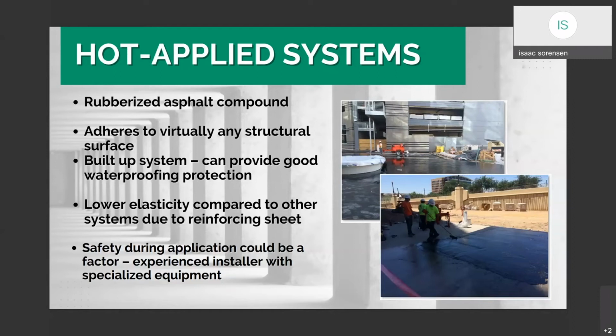where they put down like 180 mils of hot rubber, and the moisture in the substrate would often turn into steam and pinhole up through the material. So in order to mitigate that, we usually do 2 lifts with a fabric in between, about 180 mils.